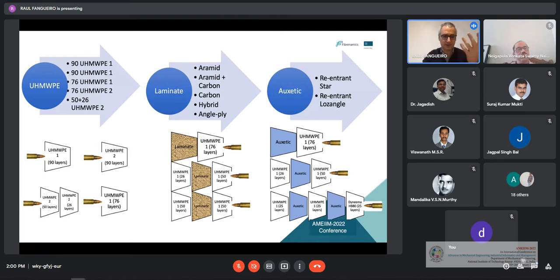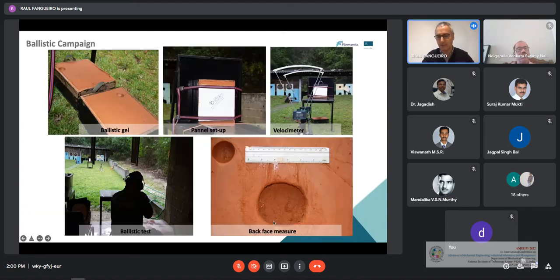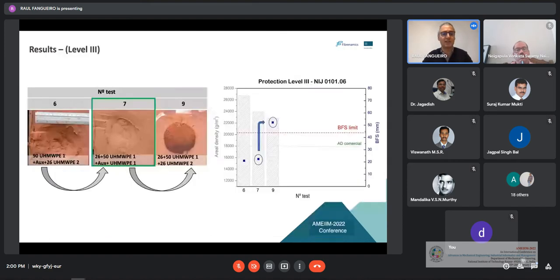And of course, this is the test setup again, and you can see that after the impact, what you see is this backface signature of the material and the deformation the bullet is creating in this backface material that is used during the test. And these are some of the results we obtained, and they are quite interesting because, as you see here in